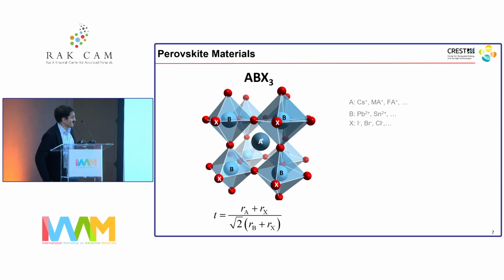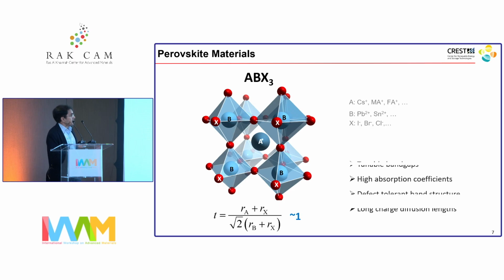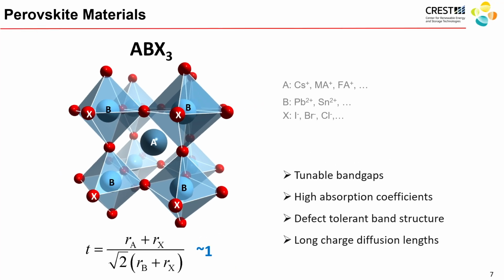And as long as the relationship between the radii of the different components obeys this tolerance factor, which would be equal to 1, there's a high chance that we'll form a perovskite structure. What makes the perovskite structure very interesting is that it has a tunable band gap, so by just changing different components of the system, very simply, you can change the band gap. It has very high absorption coefficients, as well as defect tolerance and long charge carrier diffusion lengths.